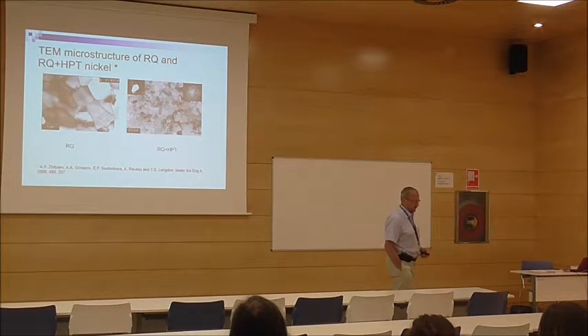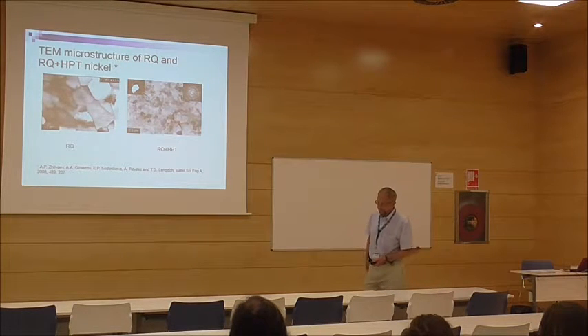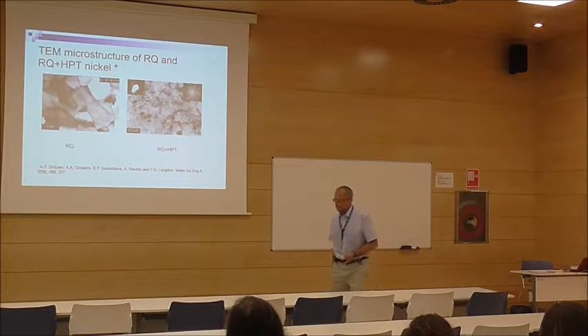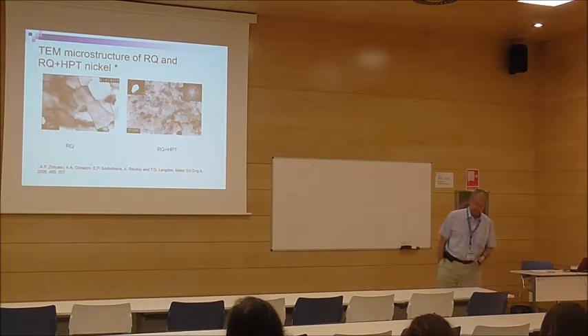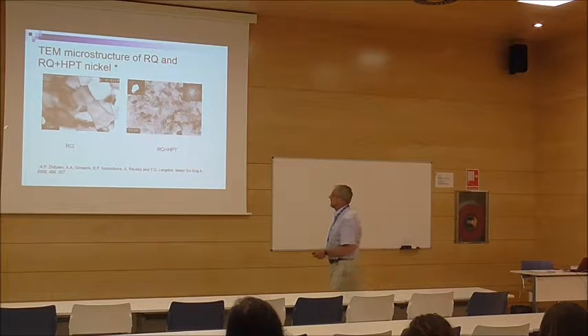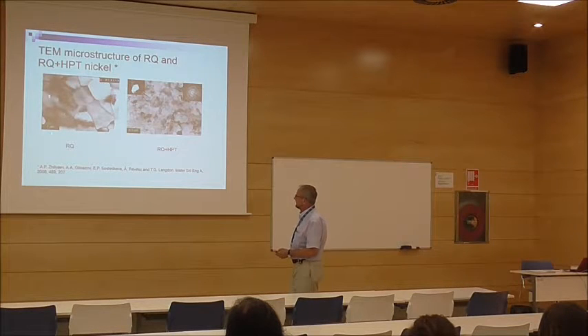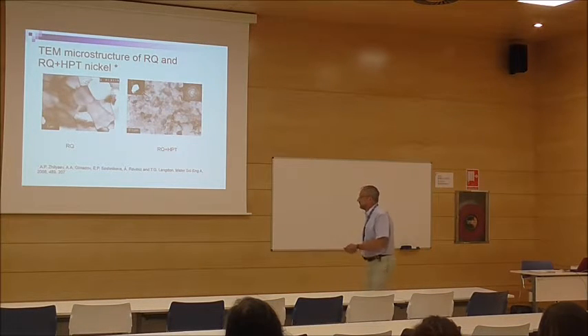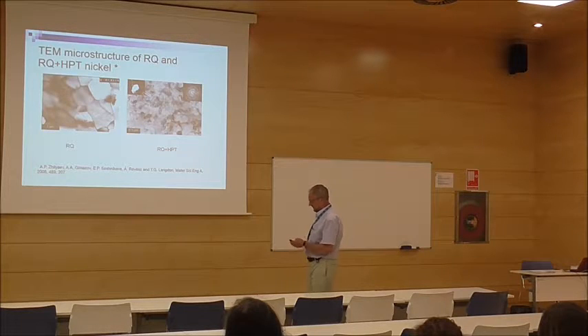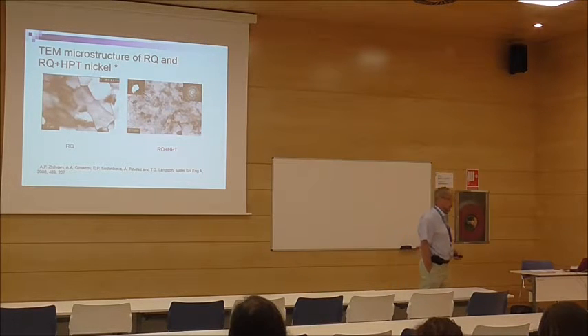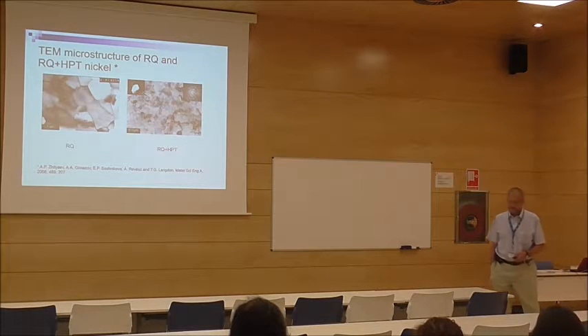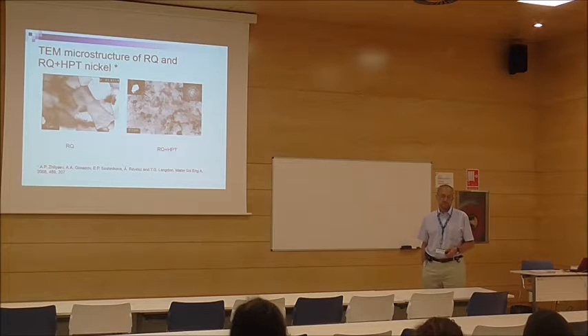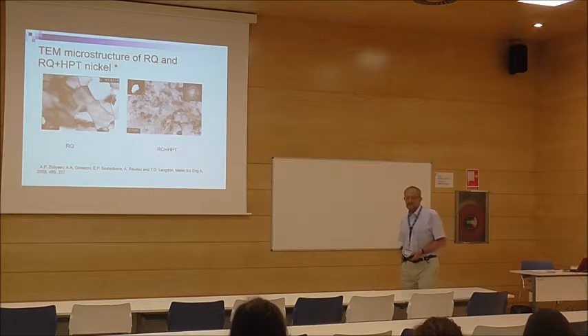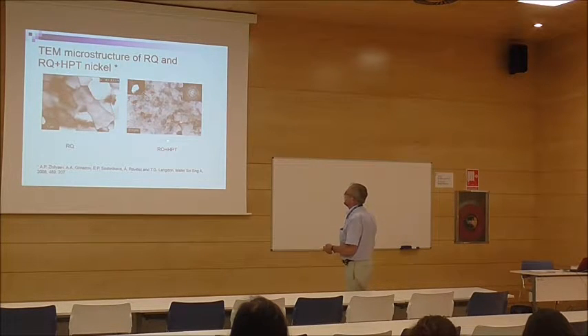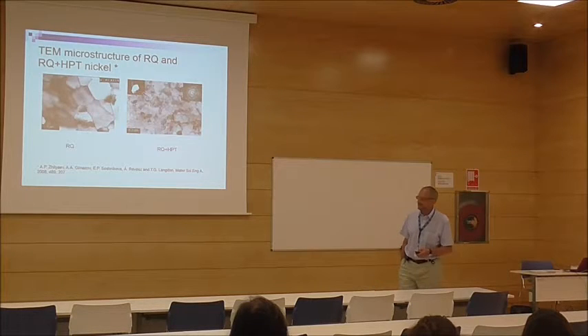So this is some work done on copper, and this is quite interesting work done on rapid quenching nickel. If you put the melt of nickel on a copper disc rotating at very high speed, you will get ribbons which have quite a big grain size. If you consolidate these ribbons with HPT, you will get further refinement, which is smaller than that one. But unfortunately, we plan at least to repeat our results for electrodeposited nickel. But it's still a mystery. We don't get any superplastic properties for these materials. Why? I don't know. If somebody knows, it would be great.